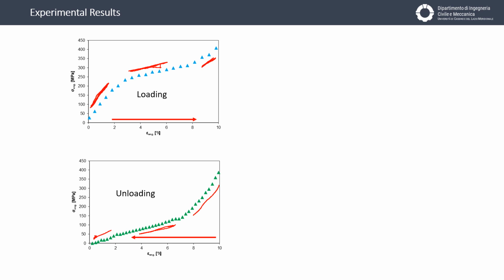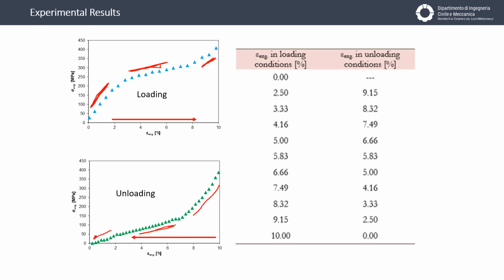energy of the austenite. In order to analyze the position of atoms at the microstructure, we have to perform the X-ray diffraction on the specimen, and we use the tools described in the previous slides, using a step-by-step technique. The steps were investigated in loading conditions, starting to the unloading condition. Then we have used the different steps, 2.5% of engineering deformation and so on, up to 10% of engineering deformation.